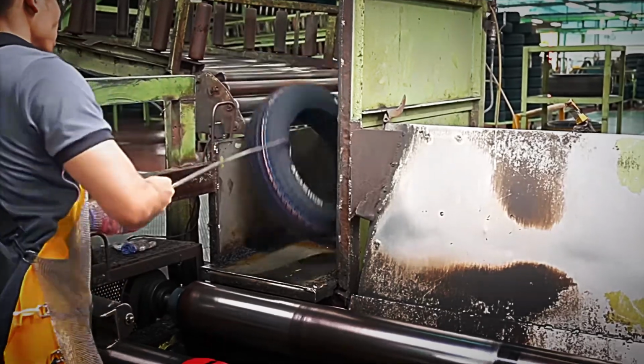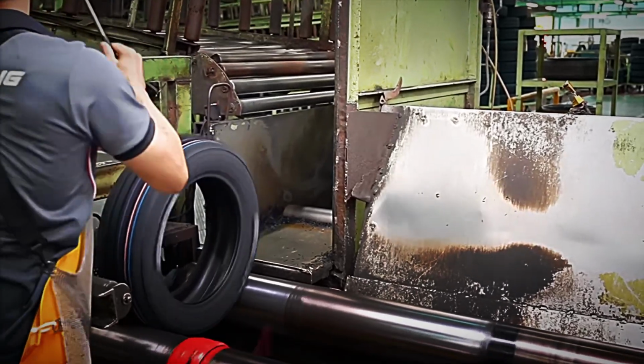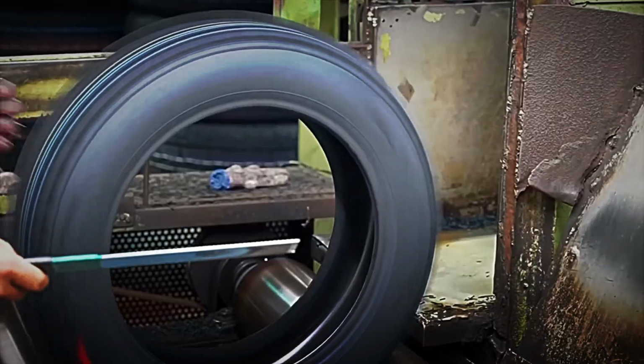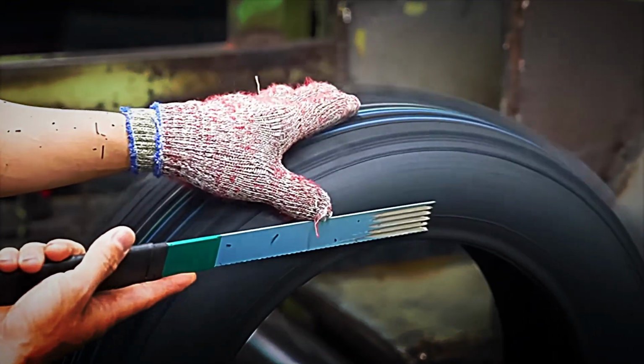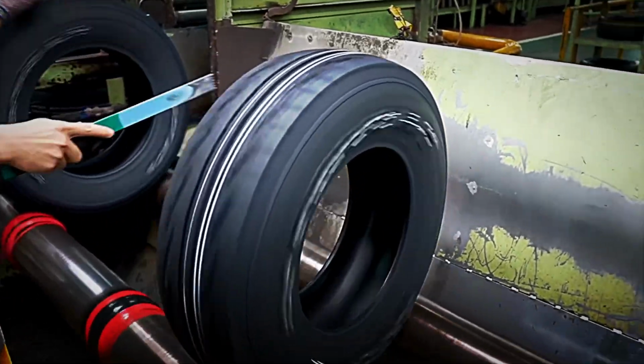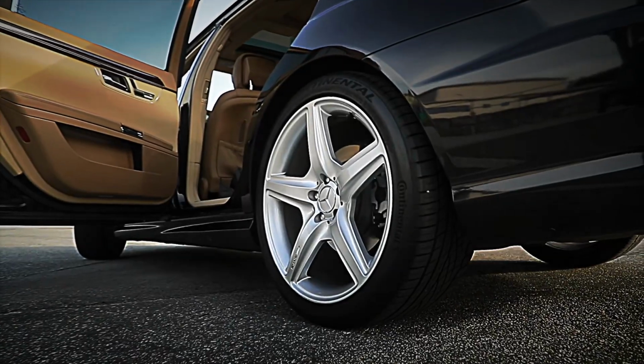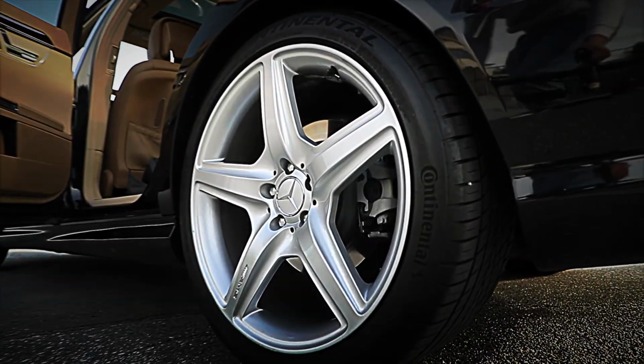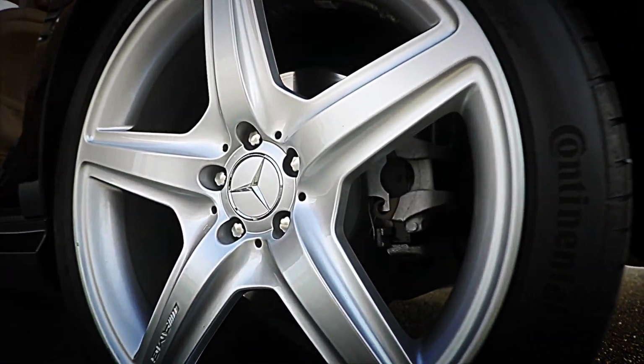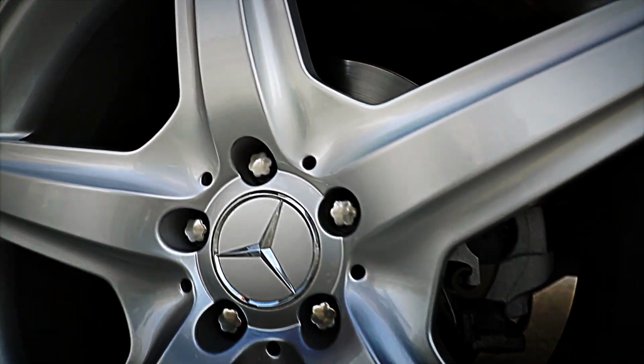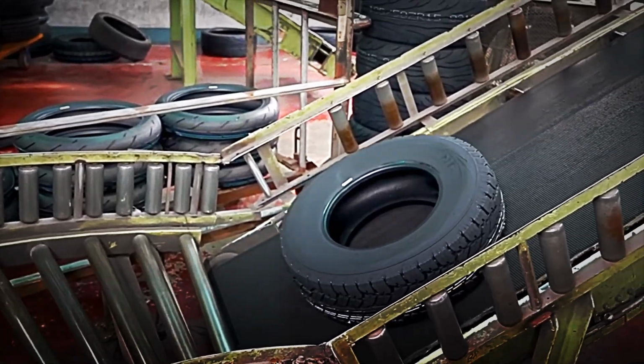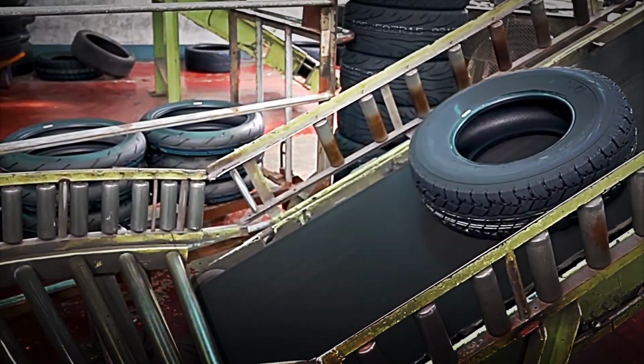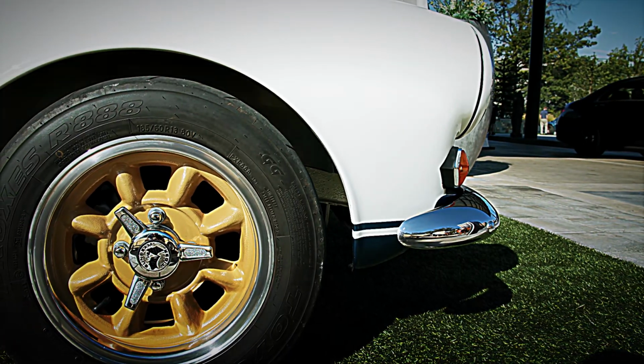Into that bicomponent matrix go additives that multiply performance. Carbon black to boost abrasion resistance and dissipate heat. Precipitated silica to improve wet traction and reduce rolling resistance. Metal oxides such as zinc oxide, which catalyzes vulcanization. And oils, resins, and waxes that act as plasticizers, antioxidants, or ultraviolet shields. The result is a compound whose mechanical, thermal, and chemical properties are finely tuned to endure millions of flex cycles, extreme temperatures, and shifting loads throughout the tire's service life.